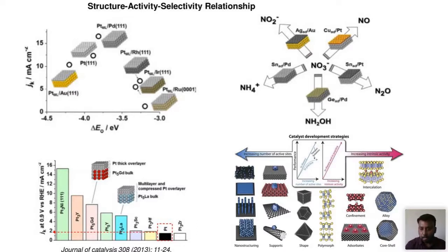Also in the nitrate reduction, you can form different products, like hydroxylamine, and also you can form ammonium ion and nitrite. So different products can be possible based on the structure and also the composition of the alloys. This picture gives you a clear idea about what is meant by an alloy and how it can influence the activity. For instance, the platinum nickel alloy performs much better, like 4 or 5-fold better than the commercial platinum catalyst.